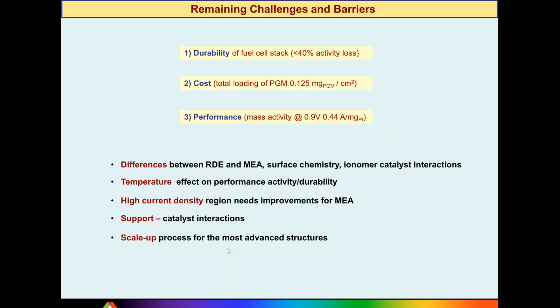Other parameters that are not greatly discussed are temperature, and also the fact that the high current density region in MEA is another topic which needs to be addressed while we are trying to decrease the total loading of platinum. Those two do not go together. Extremely low loading and high current density regions usually collide.